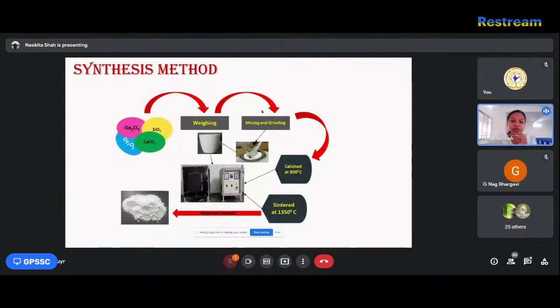These are the synthesis processes of the material. I have prepared my sample using the solid state reaction method. As raw materials, we used calcium carbonate, gallium oxide, silicon dioxide, and dysprosium oxide. All the raw materials were weighed according to the stoichiometric ratio, mixed and ground with an agate mortar and pestle for 3 hours, and then calcined at 900 degrees centigrade to remove the gases. Again the phosphor is fired at 1350 degrees centigrade for preparation of the required sample.